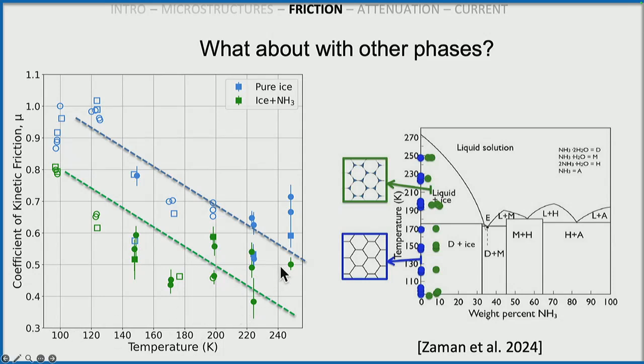So it's not the case that you create melt and now you'd lubricate your surface and friction would plummet, frictional heating would plummet. That's not the case. It seems that having this distributed partial melt reduces the friction, but you still have a lot of solid contacts that are maintaining the friction, and therefore you'd be able to maintain frictional heating. So he does an analysis in his paper about frictional heating, and he has submitted a paper where the forcing is periodic, so matching the tide.